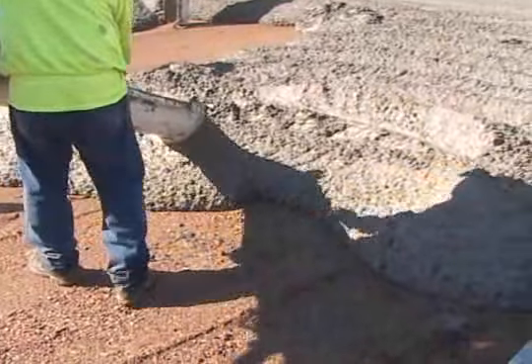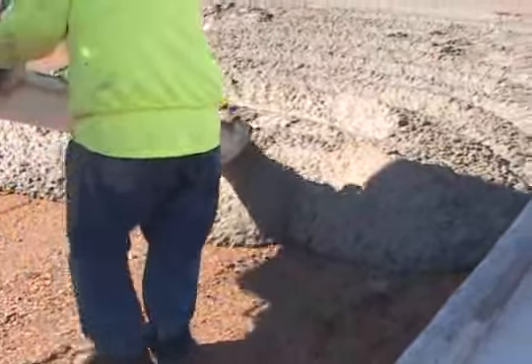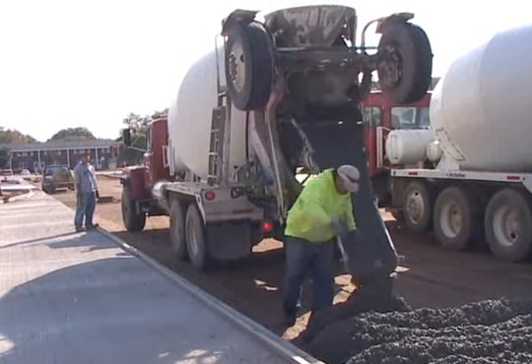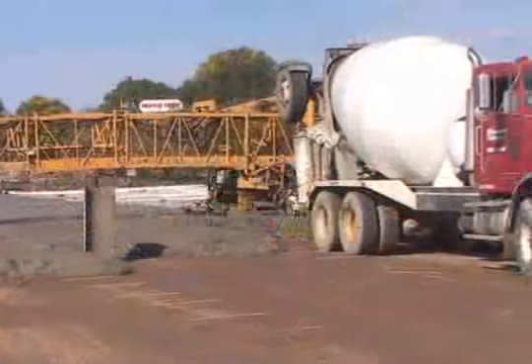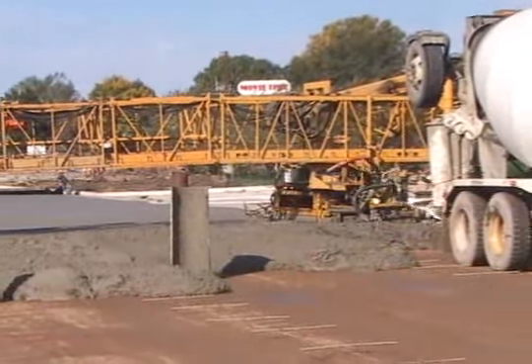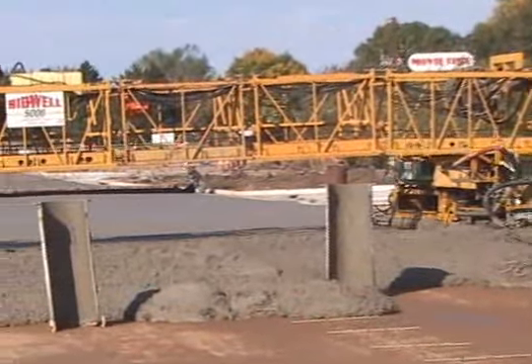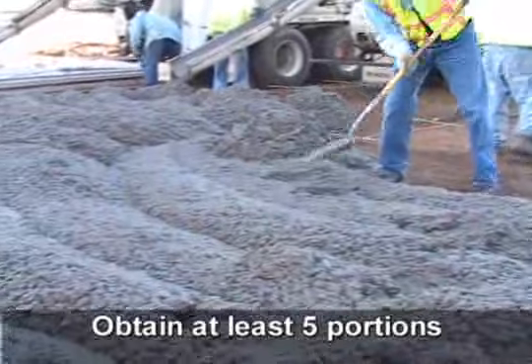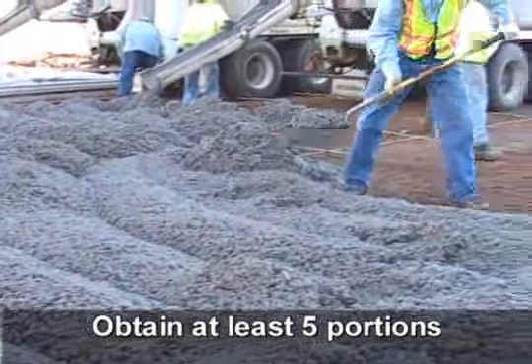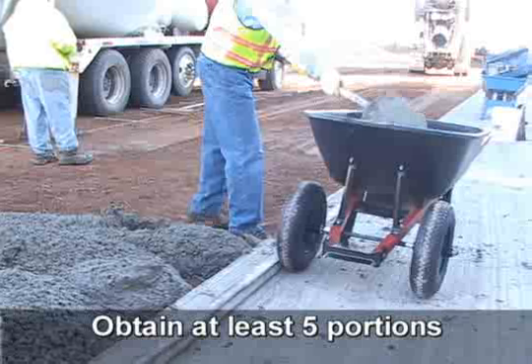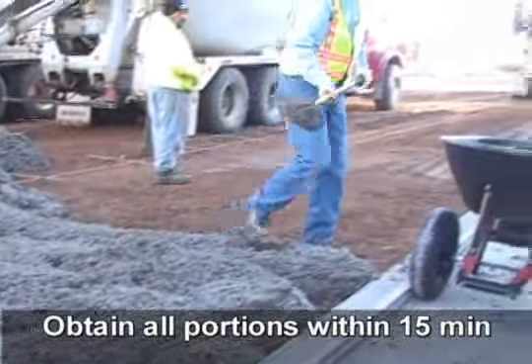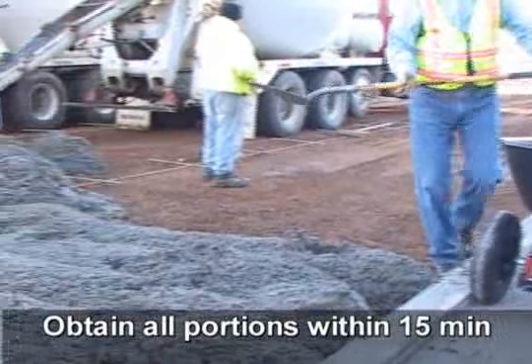When sampling concrete deposited on grade, keep the following points in mind. Sample the concrete after the contents of the mixer have been discharged, and avoid contamination or prolonged contact with the subgrade material. Obtain material from at least 5 different portions of the pile. The elapsed time between obtaining the first and final portions of material shall not exceed 15 minutes.